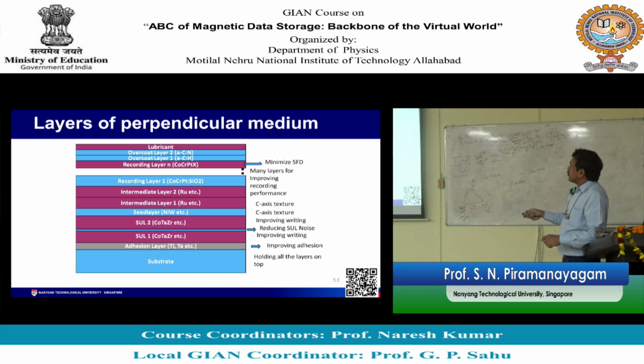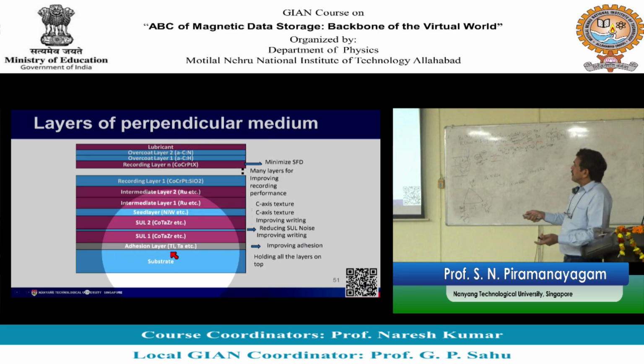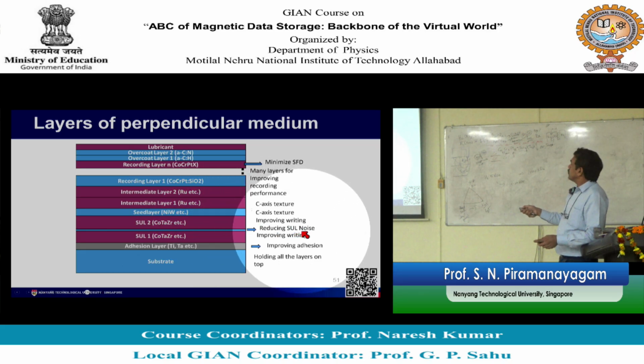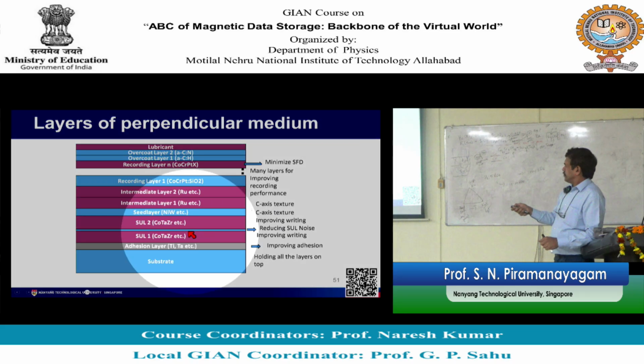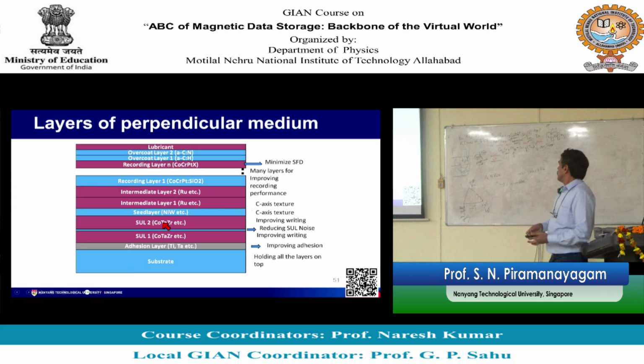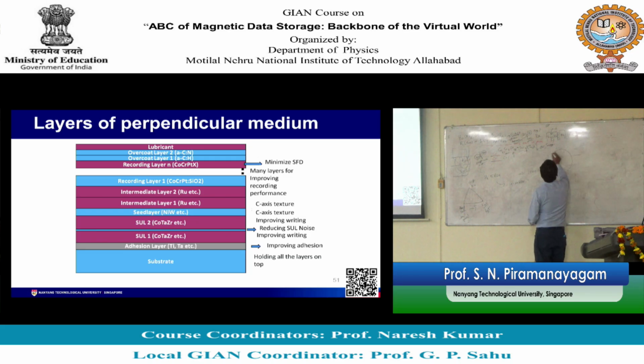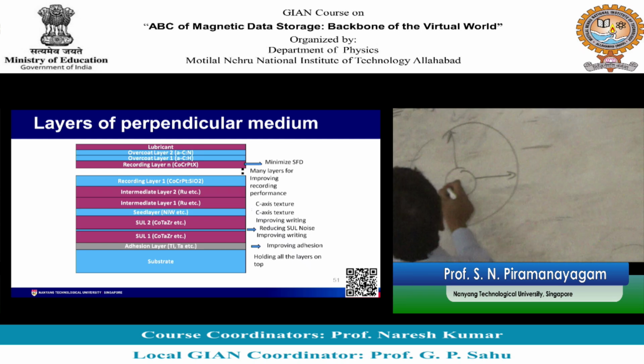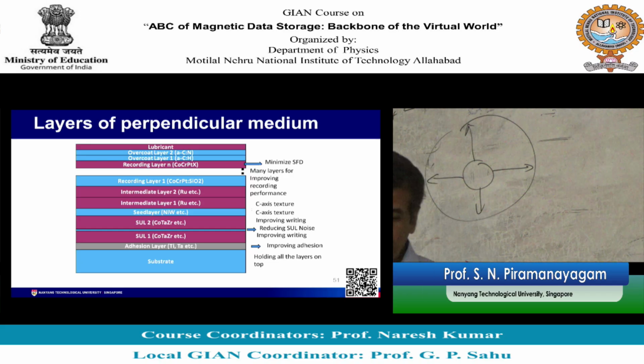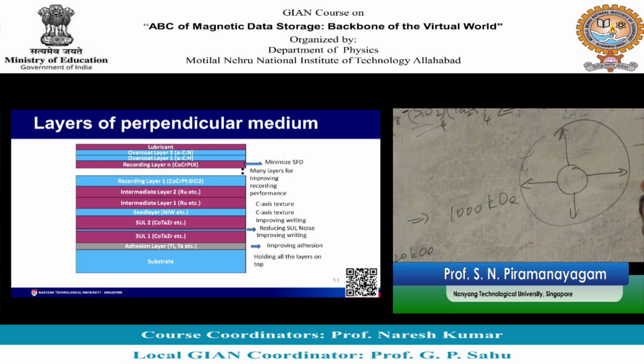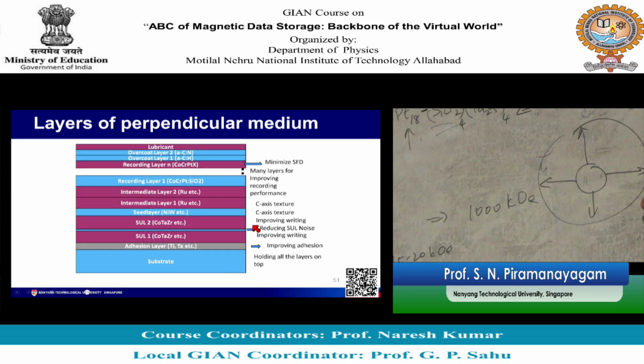Then later I taught you the different layers involved in a perpendicular recording medium. We start with the substrate, then we deposit an adhesion layer, which is like a glue for all the other layers on top. Then we start with the soft underlayer. I told you we need at least 3 layers to minimize the noise related to the soft underlayer. And I also told you that this soft underlayer has a radial anisotropy. That means the magnetization of this soft underlayer is always going to be like this. So, if you have a disk and you do not apply any magnetic field, the magnetization of the soft underlayer will be pointing along the radial direction. Those are the techniques people use to reduce the noise from the soft underlayer.